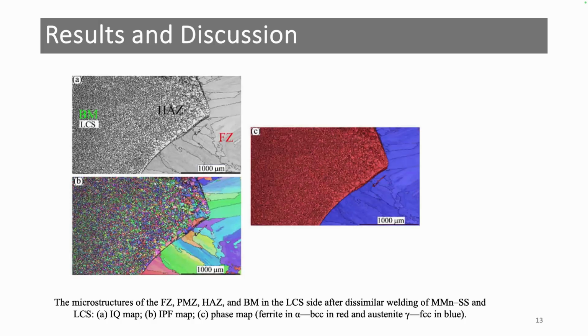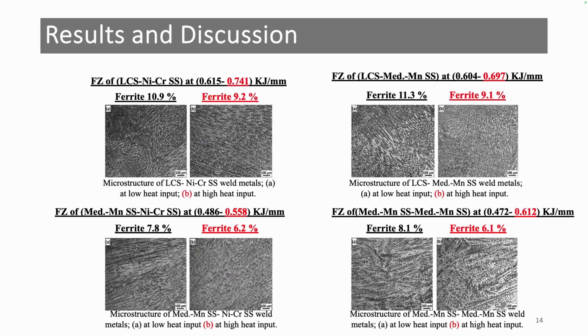The main study here was regarding the amount of delta ferrite at different heat inputs. The heat input in red is the higher one, and in black is the lower one. We calculated the delta ferrite by using a ferrite scope. We found that when we give the material higher heat input, the fusion pool will be increased and the cooling time for the fusion pool will be increased. Therefore, at higher heat inputs, the amount of delta ferrite will be decreased, because some of this delta ferrite will be transformed into austenite.